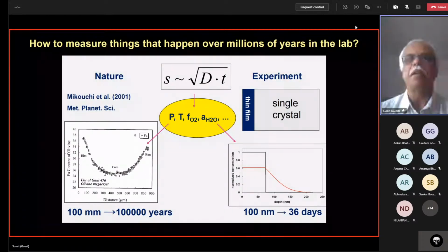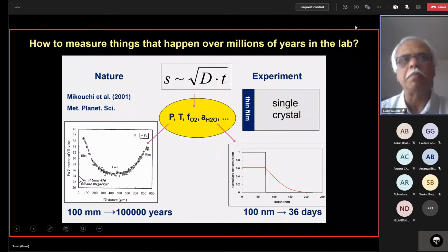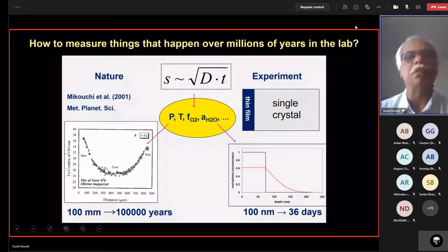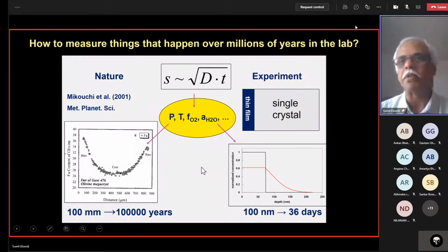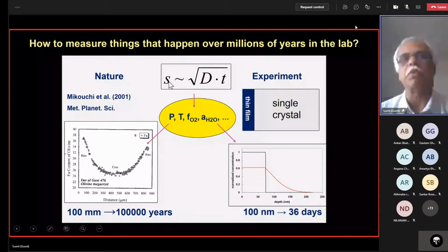And what that means is, to get the same diffusion coefficient, you can either look at large distances. This is an example of an olivine from a meteorite, where you have zoning formed by diffusion over about 100 millimeters, and that, for the particular pressure, temperature, and so forth that was relevant for this olivine, took 100,000 years. Now, by this relationship, if you could measure concentration gradients of 100 nanometers, you could see the same diffusion in 36 days. So the trick here is to keep the diffusion coefficient you want to get, but reduce the distance scale, moving down to nanoscales to see things that happen in nature over micron or millimeter scales over millions of years.